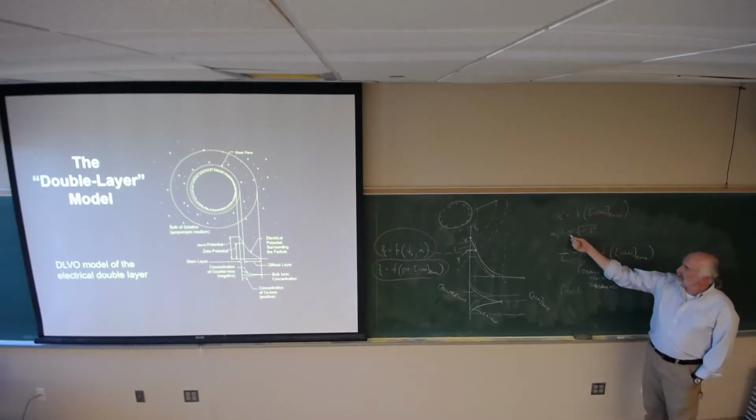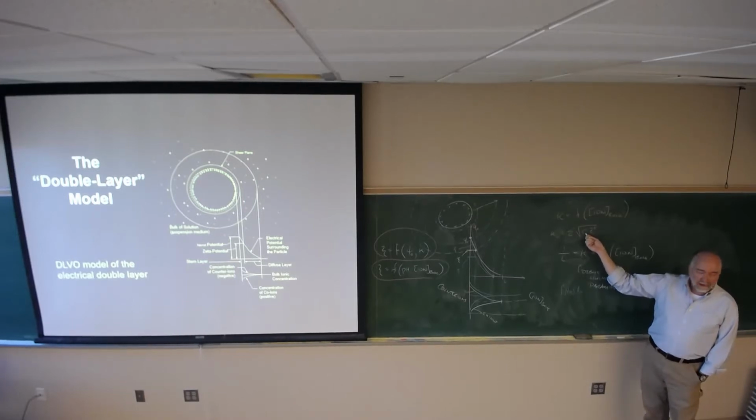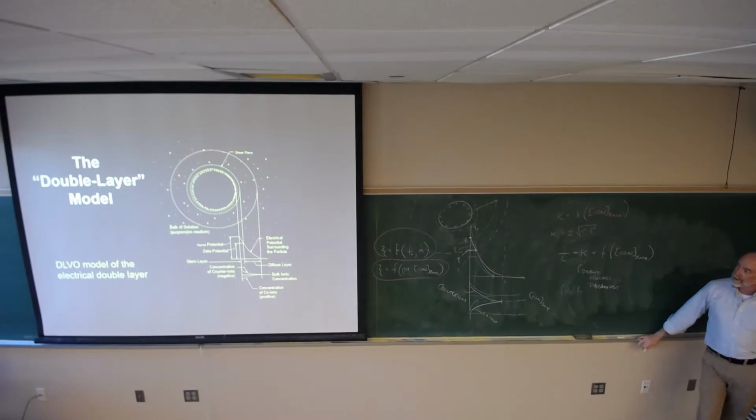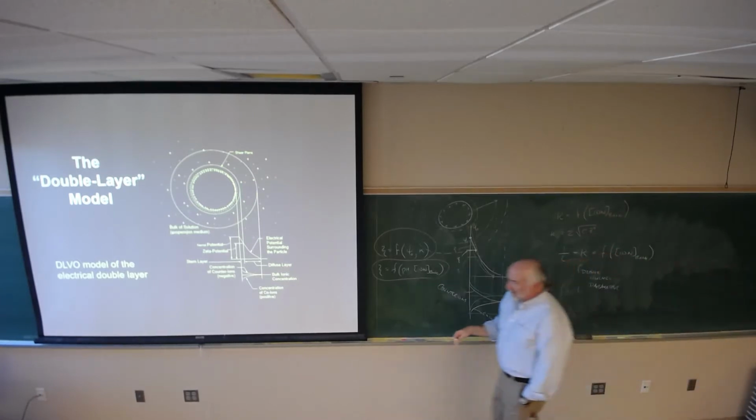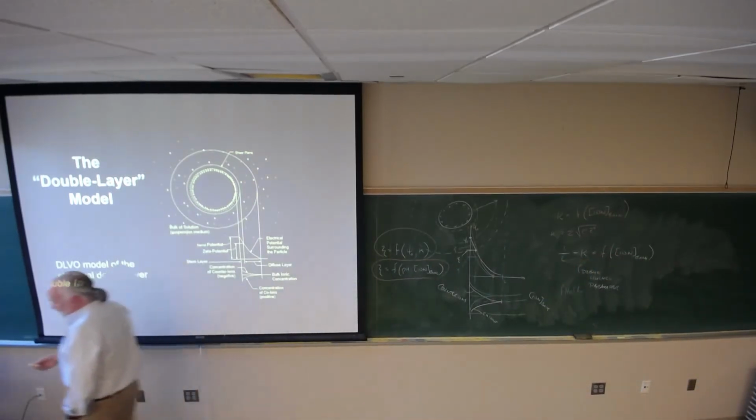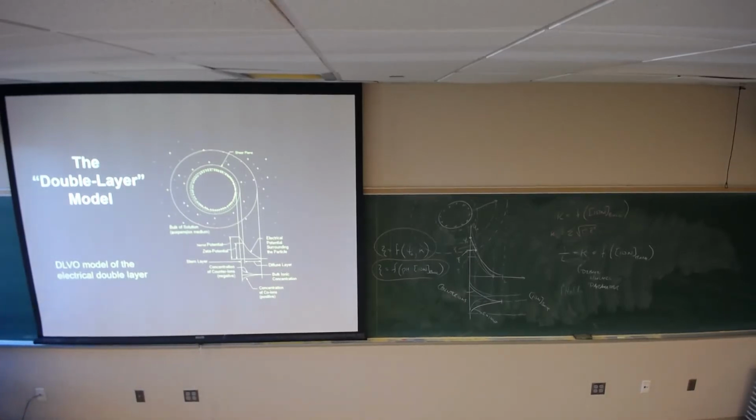Because what I have is a summation, so I can have a concentration of monovalent cations, a concentration of divalent cations, and the concentration of monovalent anions and divalent anions. I add all those up and I get this value kappa. This approximation includes a couple of terms that have to do with the permittivity of free space. There's a 1/pi or something in there. That bulk ion concentration then dictates what's happening with the double layer thickness.